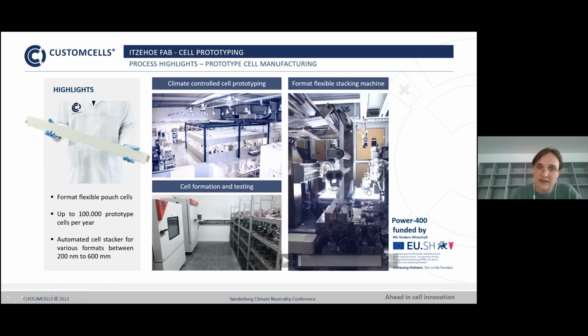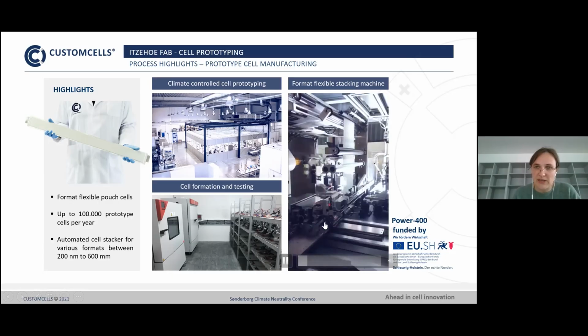You see it's a Z-folding. There is the separator film, that is the white layer here, and there is a table where the electrodes, which come from the back side here, the anode side and the cathode side, are put on the separator, and then this table just drives to the other side, and in that movement, the Z-folding is generated, and you always have a separator layer, an anode layer, a separator layer, a cathode layer, a separator layer, an anode layer, and so on and so forth. And you do this as much as you need to build up a cell with a certain capacity. I will just start the video again, and then you build up this stack.